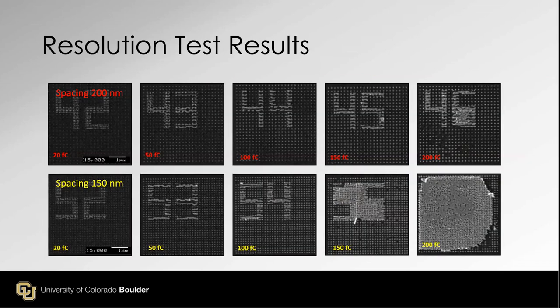This is how they look. When I have a center-to-center spacing, the distance from one dot center to the next dot, of 200 nanometers, and I'm making dot arrays using point dots. The left one is 20 femtocoulomb, femto is 10 to the negative 15, much smaller than a nanocoulomb. We use a very small unit here.